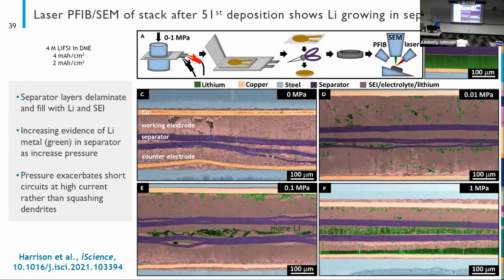And the reason we have to use coin cells is because we can't keep the pouch cell cold enough. If we try to do this with pouch cells, which we have, we actually will see heat that will have electrolyte coming off, and it starts to boil, you see bubbles. And so we're pretty confident that we keep it cold enough because we know that the electrolyte boils off when we don't. We'd like to have a bigger cryo stage that's more powerful, but we so far haven't gotten it to work with pouch cells for that reason. But it's a very good question.